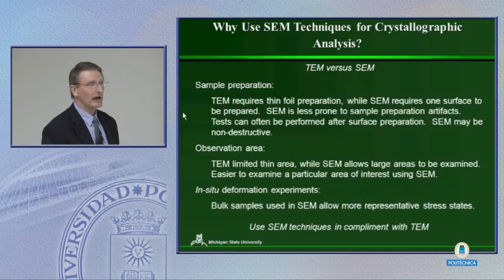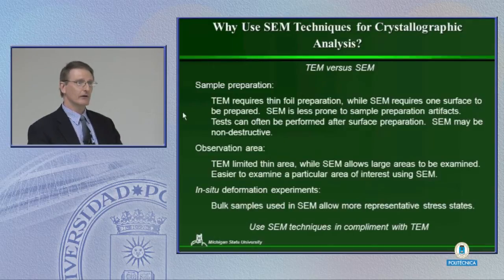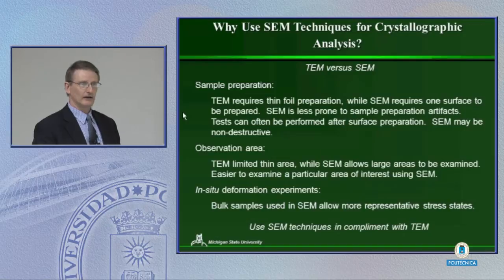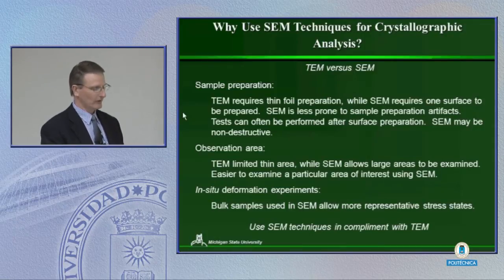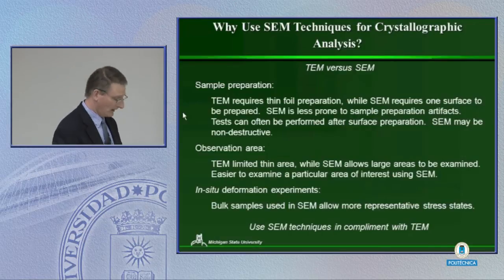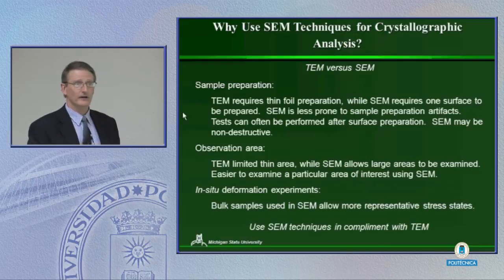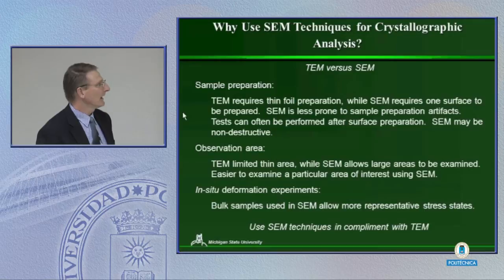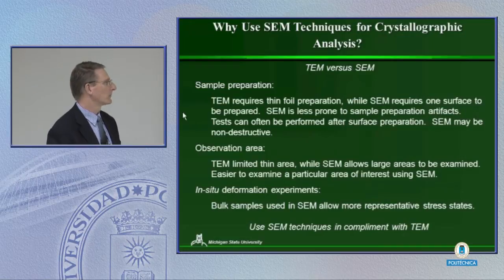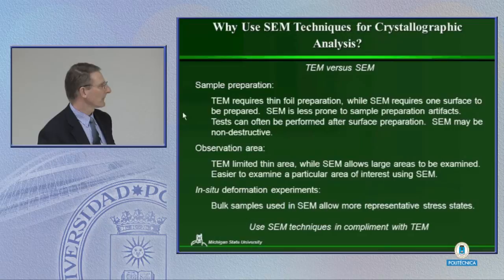Also, SEM may be non-destructive. It may allow us to test the same area through a sequence of steps and see how the material changes during the deformation processes. Rather with TEM, typically what we have to do is deform material, extract the sample, and see what it looks like. And then we're done with that sample. Also, TEM has a very limited thin area, and especially if the sample preparation is difficult, it's a very limited thin area. SEM typically allows us to look at very large areas, and this makes it much more useful to try to assess a broader scale nature of the material of interest.